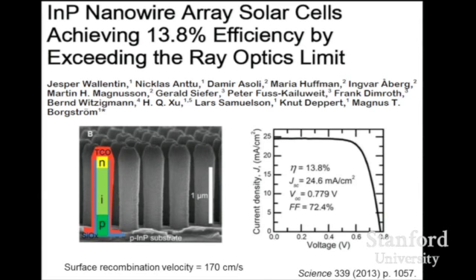I used to think nanowire solar cells would never be very efficient because you get recombination at surfaces, and these devices have a lot of surface area. But it turns out that indium phosphide has a very low surface recombination velocity, 170 centimeters per second, which is more than 1,000 times lower than it is for silicon or gallium arsenide. I don't know if anyone understands why it's so low, but it is low. And it tells us that surface recombination is not necessarily something that has to kill a nanostructured device.